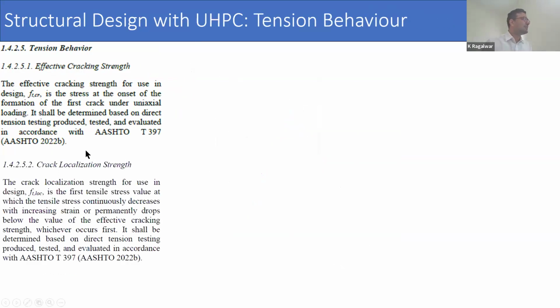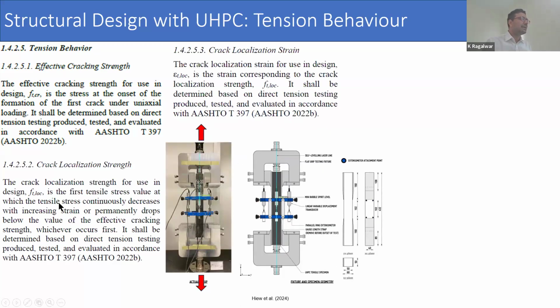In terms of tensile behavior, the effective tensile cracking strength is the onset of the formation of the first crack. And then crack localization, which is another parameter used to define the tensile behavior, is basically the first tensile stress value at which tensile stress continuously decreases with increasing strain and permanently drops below the value of effective cracking strength. So the cracking stress after which the stress with increasing strain does not rebound, it just keeps lowering, the strain related to that stress is known as localization strain.